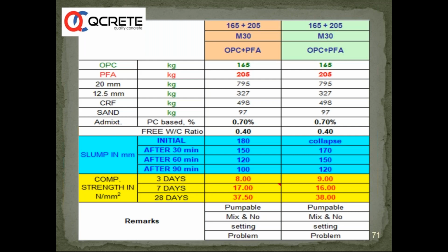We also did some trials towards high volume fly ash concrete, where we used 165 plus 205 for attempting to make M30 concrete actually. So you can see at a water cement ratio of about 0.4 with a PC based admixture, we had proper slump, and then the 28 day strengths were okay, acceptable actually. You cannot exactly be happy as a M30 concrete, but okay, you have come very close to M30 concrete.